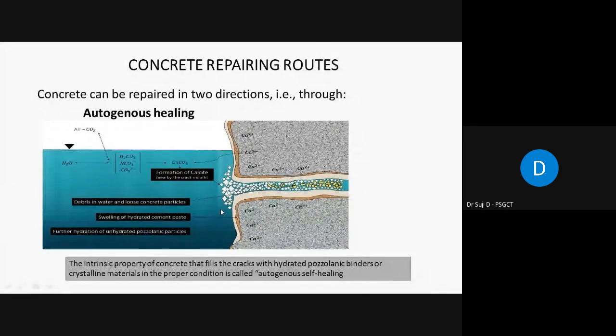So in the first step, see, there is water here. Once the crack is open, we have a cement paste, right? This cement paste sometimes consists of some unhydrated cement particles. So whenever the crack opens and meets the water source, moisture, these unhydrated cement particles start hydrating. During the hydration process, a byproduct called calcium hydroxide is also formed in parallel, right? This calcium hydroxide reacts with the CO2 which is available in the atmosphere. That CO2, in the presence of moisture, dissolves and forms carbonic acid, and this calcium hydroxide reacts with it and finally forms calcium carbonate, a white powder, right?